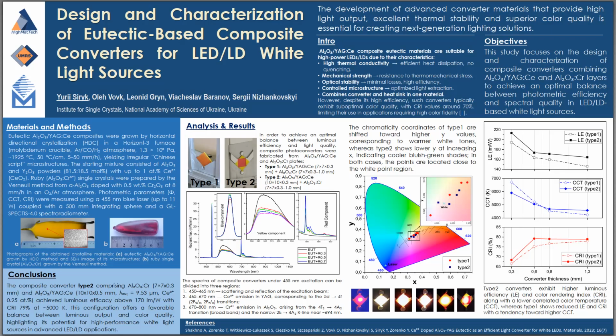Eutectics were grown by horizontal directional crystallization with cerium concentration up to 1 atomic percent. Ruby was grown by the Verneuil method with the chromium concentration around 0.2 atomic percent. Two parts of each converter were joined using a heat-resistant polymer resin, ensuring mechanical stability and optical transparency at elevated temperatures. Two types of composite converters were fabricated, which differed only in the size of the eutectic plate.